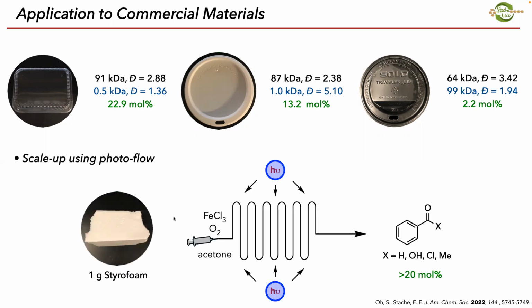But the good news is that we can also scale this process up. So in these examples up here, we're doing this on a very small scale, but we can use a photo flow process, which means essentially we have a long tube and the light is shining on it. And so we get really good surface area, really good light penetration. And so in that way, we can scale up the polystyrene degradation. This is just a gram, but we can now do this in less than a day, right? Instead of taking the 2 to 5 days that we had in batch, we can do this much more quickly. And we're working with another company to further optimize this process. We can show that we can do this on kilograms and then hopefully metric tons, which is the scale of polystyrene waste.